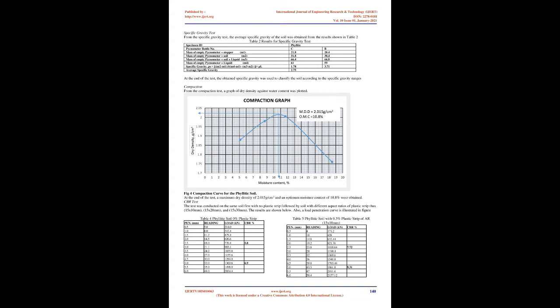Discussion of results. From the index property test conducted, the soil has a specific gravity of 2.75, which from the specific gravity chart indicates it contains silt and clay. It has a liquid limit of 23.0, a plastic limit of 12.6, and a plasticity index of 10.4. According to the plasticity chart, the soil was classified as CL, clay with low plasticity. The maximum dry density and optimum water content as determined by the compaction test were 2.015 g/cm3 and 10.8%. This means that beyond the optimum moisture content the dry unit weight of the soil would reduce.